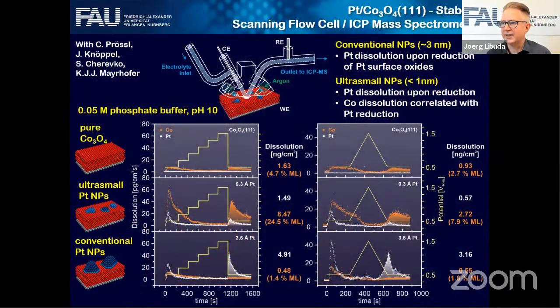Now, finally, let's look at the stability of the system. And this is really surprising. Yeah, so we do this scanning flow cell ICP mass spectrometry experiment to see how stable the system is. And we did this experiment with cobalt oxide. Here you see that cobalt oxide really doesn't dissolve if you ramp up and down the potential. If you use these big nanoparticles, ramp up and ramp down the potential, there's dissolution of platinum. That's expected. Now, if you reduce the platinum particles, part of it dissolves, that is expected. But the surprise is when you're doing this experiment with these very small particles, what you see is actually very little dissolution of the platinum, but instead cobalt dissolves. So how can you explain that?